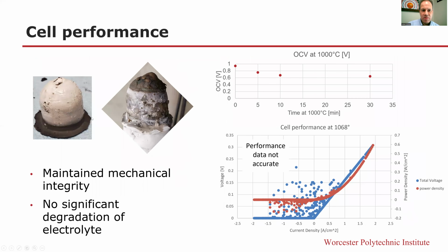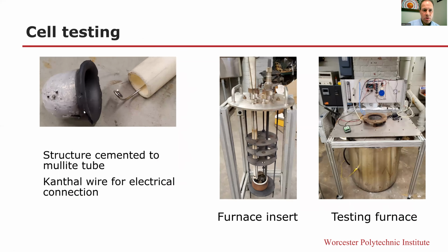We've just made these small kind of thimbles supported by the lanthanum calcium manganite electrode here. So you can see the very thin, it's about 40 microns of zirconia on the outside, and we used a Kanthal wire for electrical connection here.